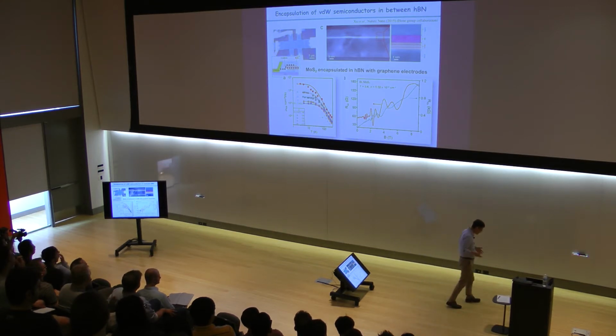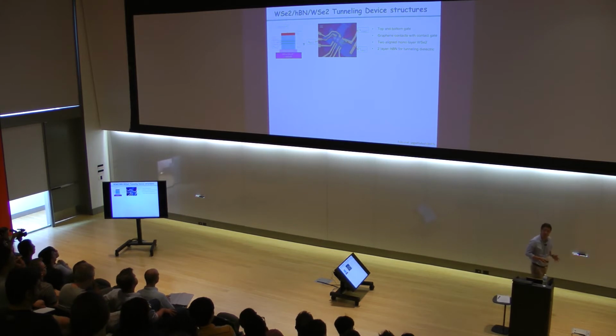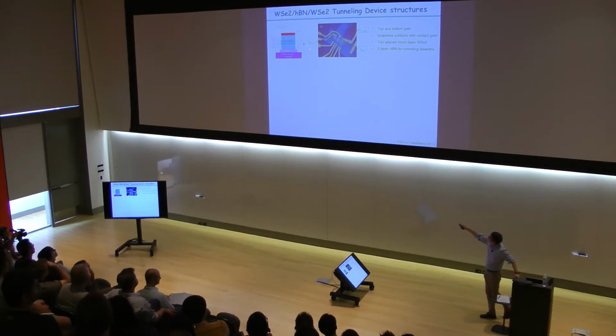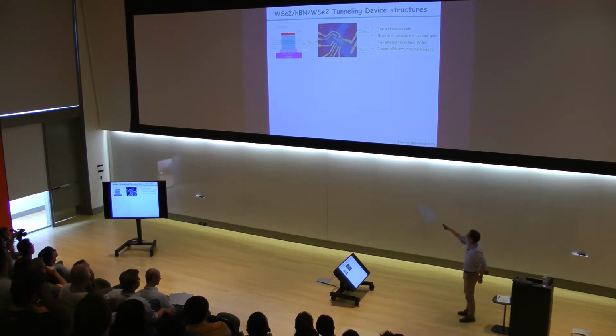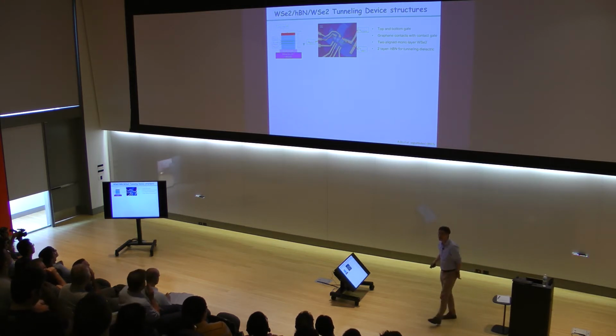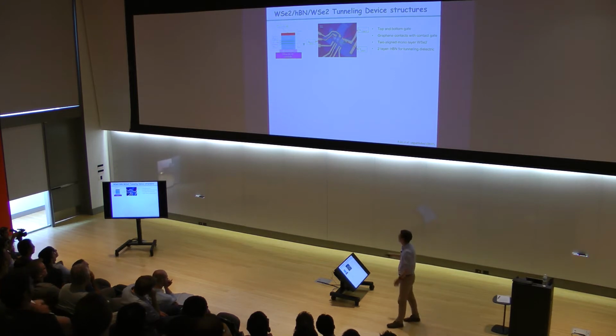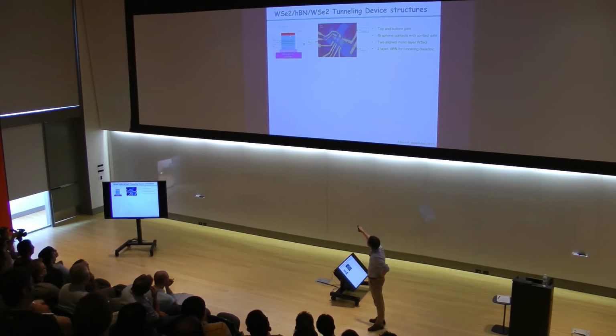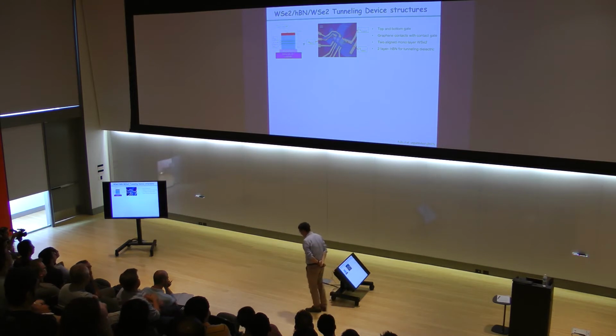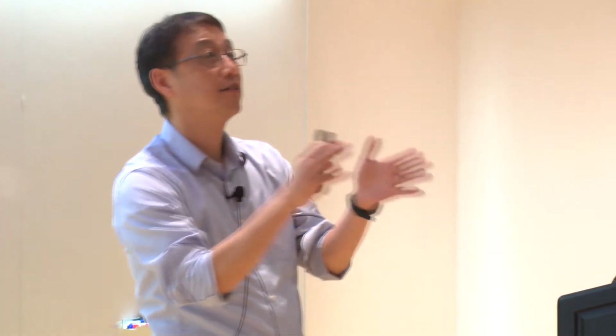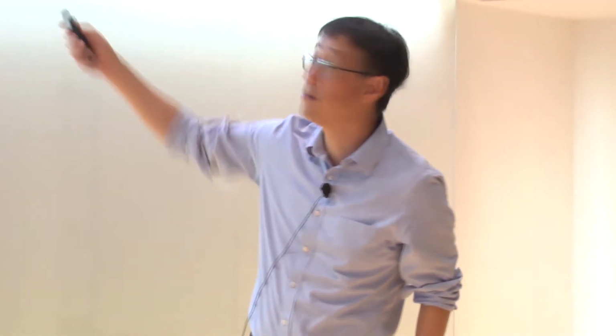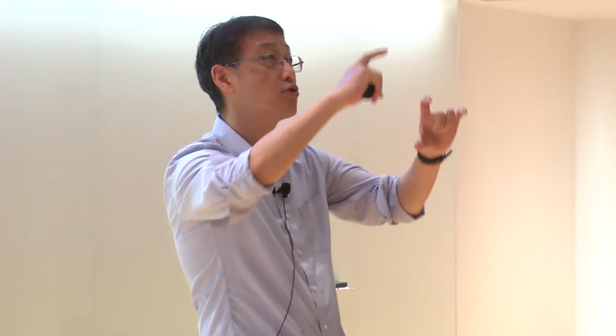Not only just magnetic field and low temperature quantum devices, but you can also make some of the other known quantum devices beyond CMOS. Here is another good example. In this particular example, sorry about the small characters, but here is tungsten diselenide, a P-type semiconductor, and another tungsten diselenide, but in between them we insert a very thin layer of boron nitride as a tunneling layer, right? Again, this is made out of successive stacking. And then you can clearly see that between these two layers, because the boron nitride is so thin, it's a good tunneling device. Now, this type of tunneling device is what we can make with the so-called quantum well resonance tunneling device out of semiconductor heterostructures. The big difference here is we have the gate from top and bottom such that we can control the band alignment between these two materials, right?